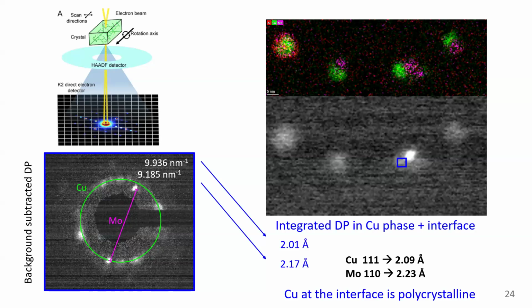But to answer your question, it's going to depend on what catalyst material you're working with. Some materials will be more stable, others will be less stable. And so, to answer the question of whether we're able to form alloys even, you can see that here we're forming Janus structures, and so there's phase segregation. So even with gas phase synthesis, for this particular material space, we still observe segregation because of the differences in the crystal structure.